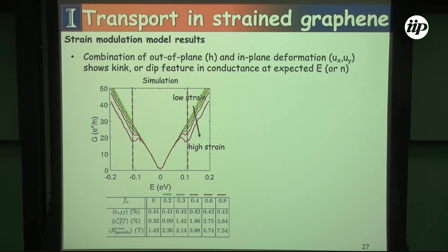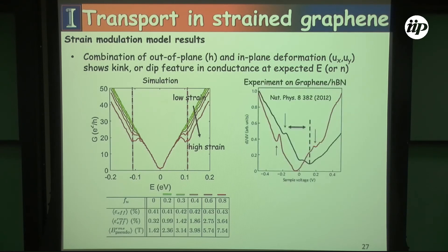When we put this strain model in, we can clearly see that as we increase the amount of strain — going from low to high strain at experimentally realistic values — the percent change in the lattice constant is about 0.43% at its highest, giving a pseudo-gauge-field magnetic field of about 7.5 Tesla. These different curves correspond to different couplings between the graphene and silicon nanoparticles. When we check our simulations against the boron nitride case, we see similar superlattice Dirac points, symmetric in our model because we don't include the next-nearest-neighbor asymmetric coupling term.